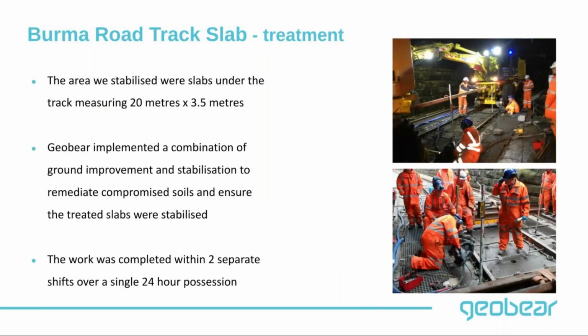The main driver of the deterioration was very poor drainage conditions underneath, combined with loose uncompacted materials underneath the track. So what we were commissioned to do was to lift the slab track to the desired position, and also inject the material into the loose, soft granular material underneath, to strengthen its properties. And we were able to complete this work in two separate shifts over a single 24-hour possession.